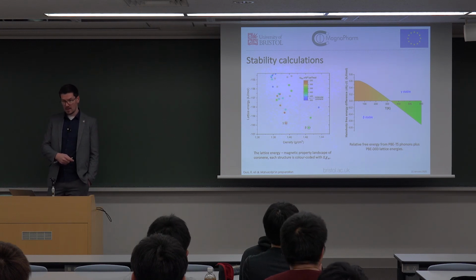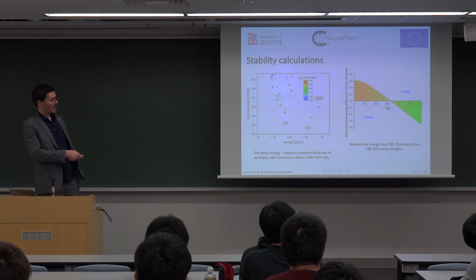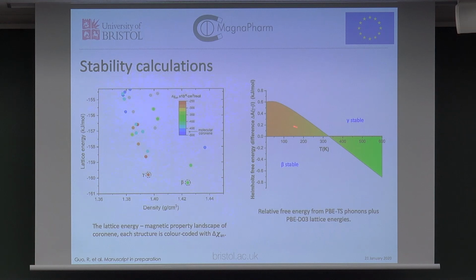And this calculation on the right is a phonon calculation to try and simulate temperature and work out where the crossover is. And you can see here, beta is more stable at low temperatures, gamma is more stable at high temperatures, with a crossover at about 330 Kelvin. So can we see that if we lower the temperature?